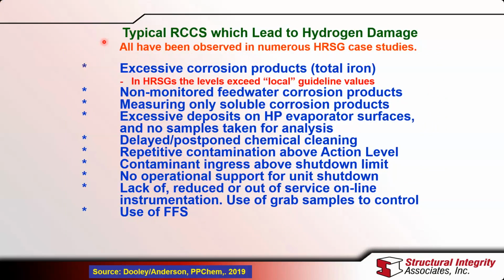These are the things that you need to look for to see if hydrogen damage is going to be a possibility in your HRSG. The main one I've already mentioned is excessive corrosion products. This is the total amount of iron that moves from other places in the cycle, from the lower pressure cycles, the low pressure evaporator, low pressure economizer, IP or HP economizer, and deposits out in the HP evaporator. And most often you can see that these levels of iron exceed the local guideline values. And I'll show you the guideline values in a minute.